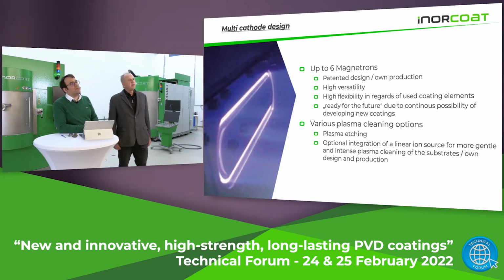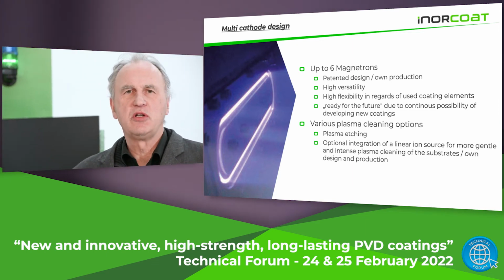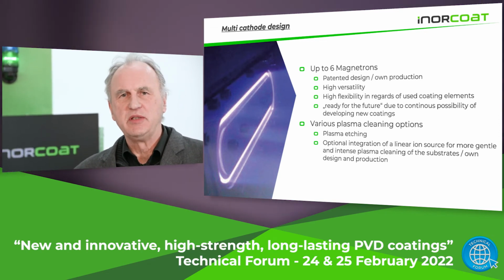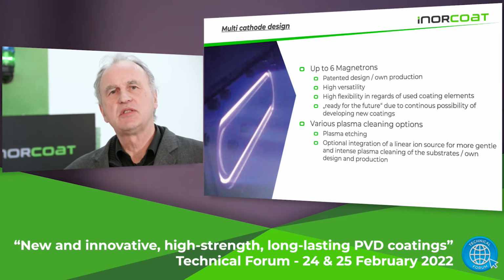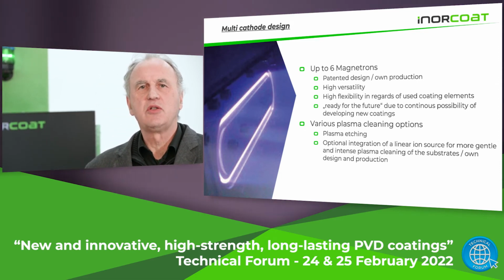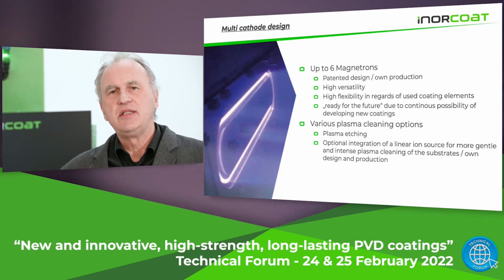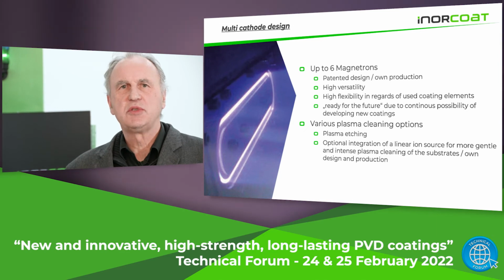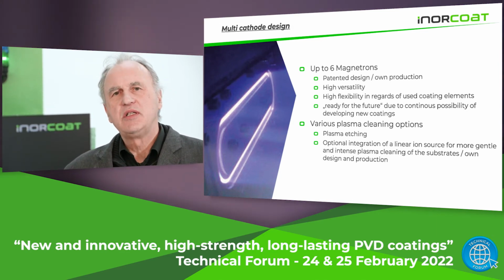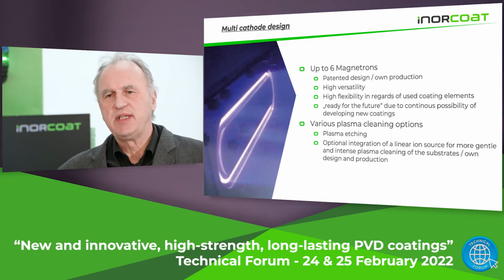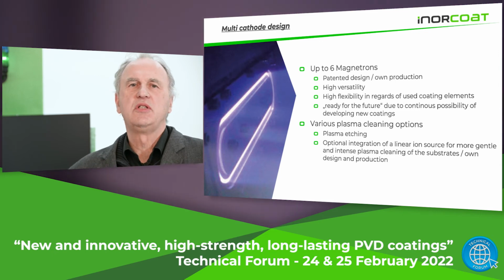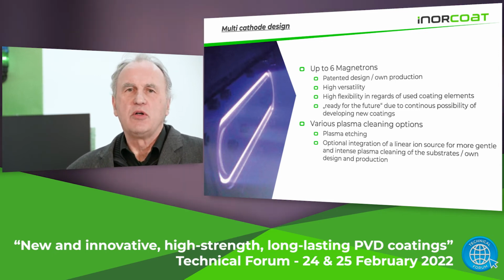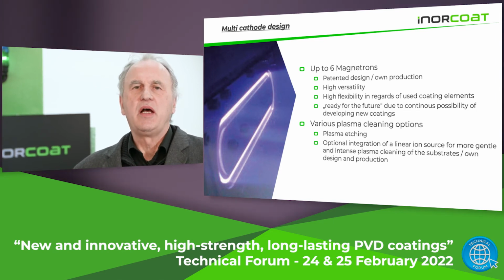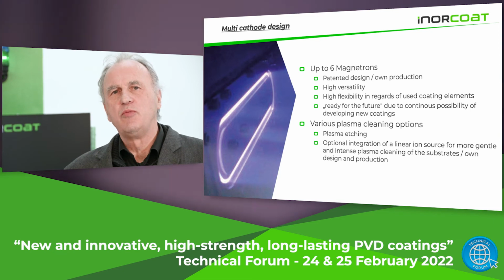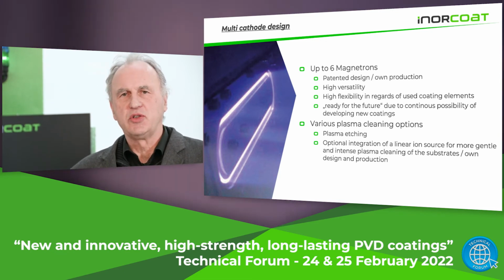If the computer control and the HMI could be considered the brain of the machine, then the cathodes, or what we call the magnetrons, are the heart of the machine. The atoms are liberated from the magnetrons and directed also by the magnetic field of the magnetrons towards the substrate. And like this, we guarantee that on the substrate the ceramic is formed with the metal inclusions. Additionally, in PVD coating, you need to activate the surface prior to the deposition to guarantee a good adhesion. This is done both by plasma cleaning in situ, or optionally, if more profound cleaning is needed, by a linear ion source.